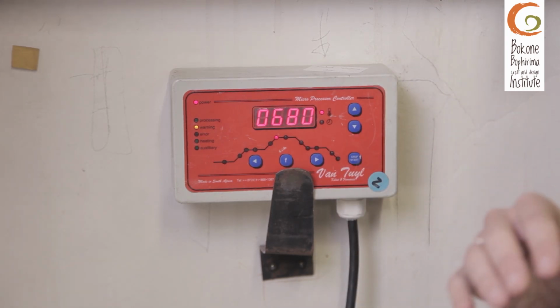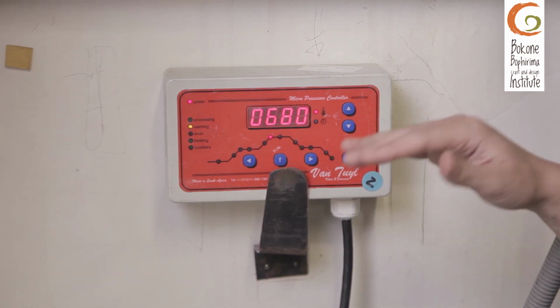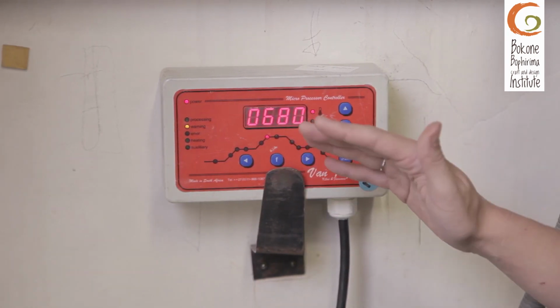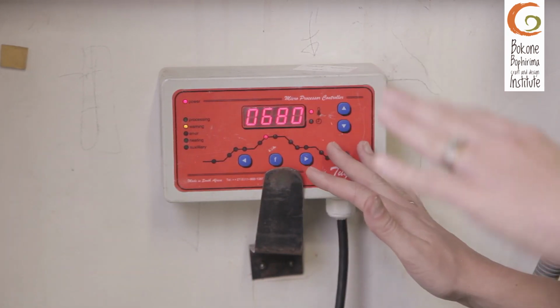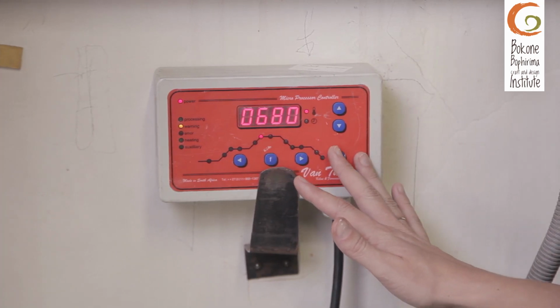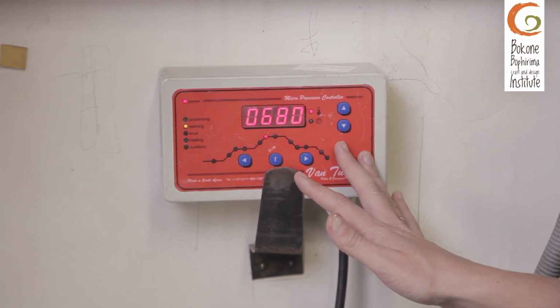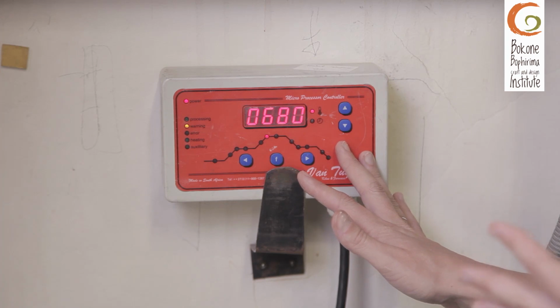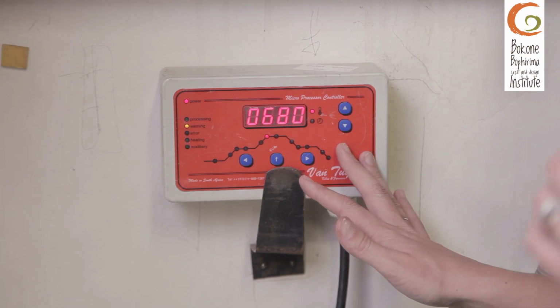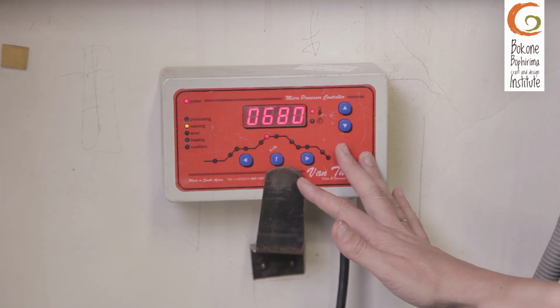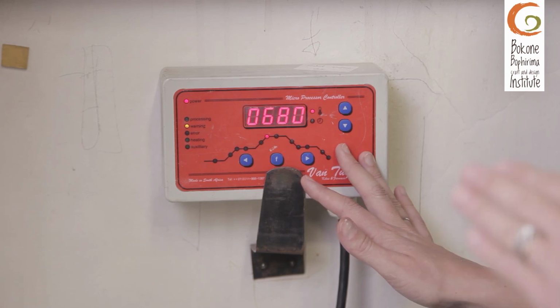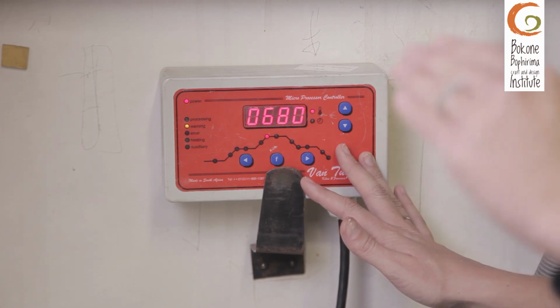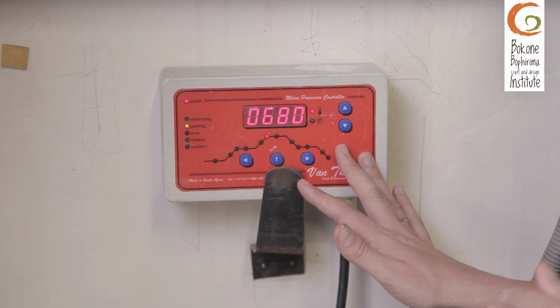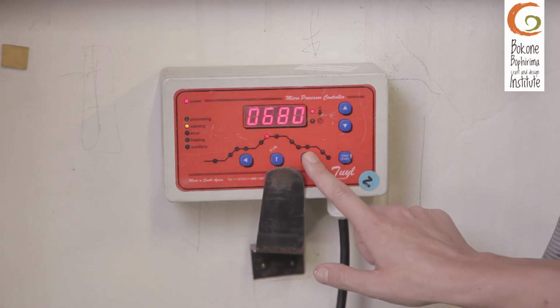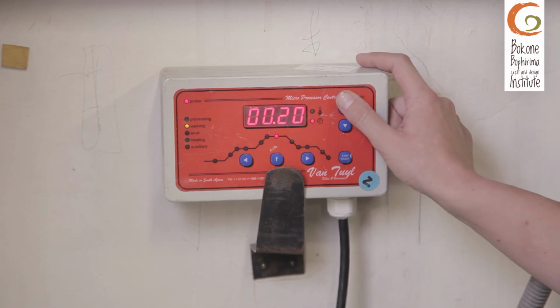If need be, and we need to hold the glass there, for instance, for an hour, half an hour, rather hold it at a lower temperature of 680 than trying to ramp it higher, because anything higher than 700, especially with float glass, we tend to get devitrification, that crystal layer on top. So if we can keep our top temperature lower than 700, we will be less chance of devit. So I'm going to hold my glass there for 30 minutes.